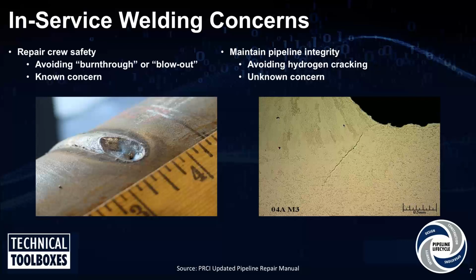And again, it goes back to the aspect of there's something in the pipeline cooling the weld faster than it naturally would. And as the welds cool faster, those welds become more brittle. And a brittle weld tends to be much more crack susceptible than other welds. And I'll get into a little more detail with hydrogen cracking a little bit later.